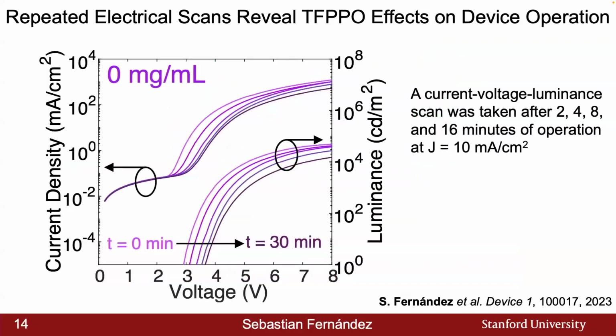So first, looking at the repeated electrical scanning measurements, I'll briefly define what this measurement setup is here, in which the electrical scan is a current density voltage luminance scan. We take it for a fresh device at time equals 0. Then we stress the device for 2 minutes at 10 milliamps per centimeter squared, followed by another scan, followed by 4 minutes of operation, followed by another scan.